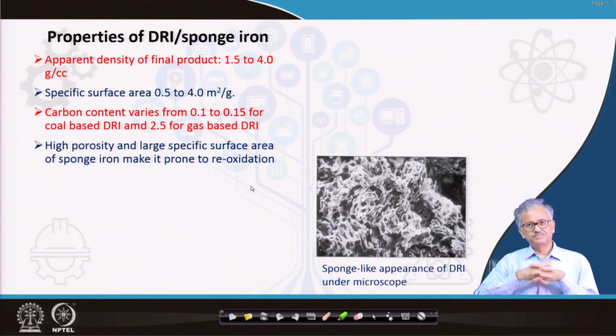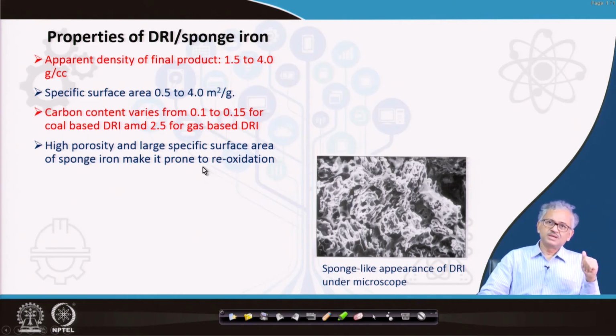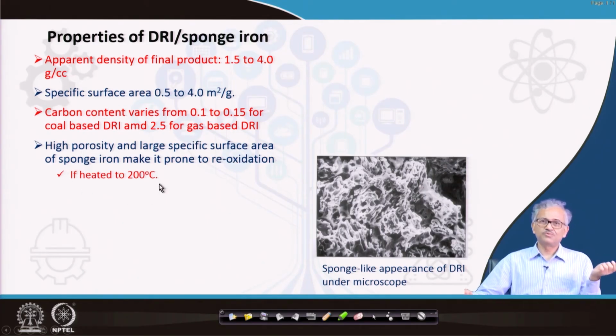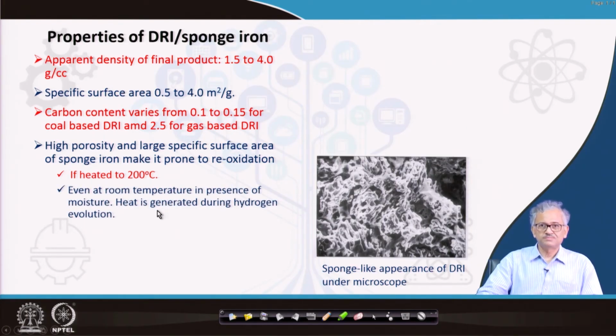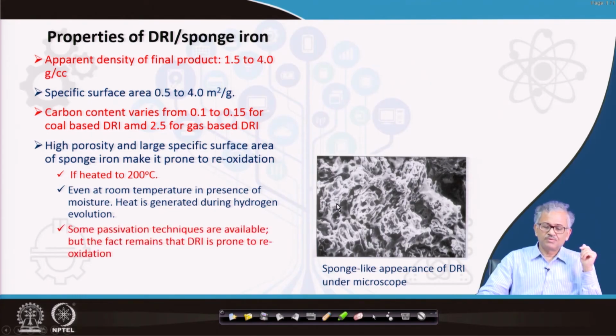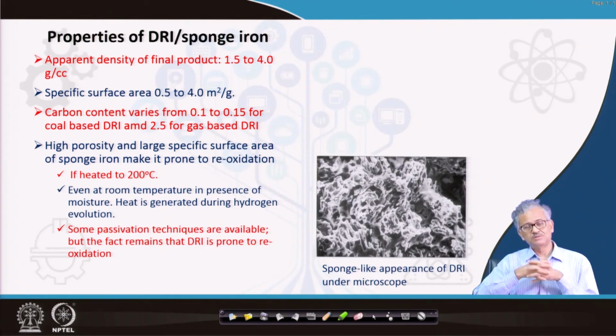Another thing: this high porosity and large specific surface area increases the reactivity of the sponge iron obviously, but at the same time, because of this, the sponge iron is also very prone to reoxidation. That is not good, because after metallization, if it gets reoxidized, your yield will be less. So how does it get reoxidized? If sponge iron is heated to only 200 degrees centigrade, that is why you cannot preheat it, at 200 degrees centigrade it will be reoxidized. Even at room temperature in the presence of moisture, and hydrogen generation basically increases the temperature. Therefore, whatever it may be, this applies to sponge iron, especially gas-based sponge iron.